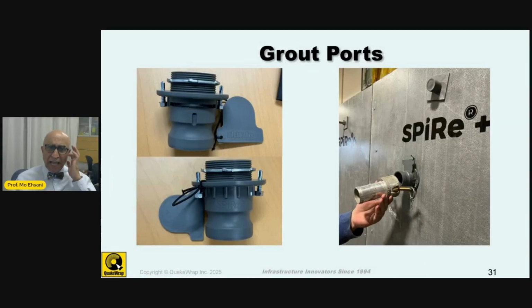So we have grout ports, as you see here. These grout ports, if you want to put them on the sides of your girder or on the bottom of it, you can put these, and then with these cam locks, they can connect, and from here you inject the grout. Once it is done, there's this guillotine that you put in here, so you stop the backflow of the grout, and then you disconnect your pump and go to the next grout port and continue doing that operation.